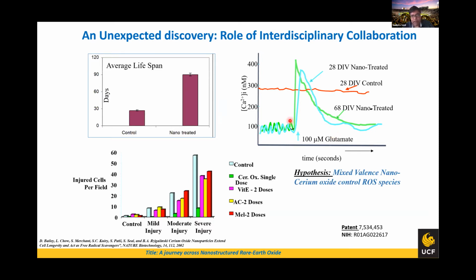At the same time, we got a grant. One of the comments from the panel was, how does it compare with the normal antioxidant type material if you're selling the cerium oxide as an antioxidant? And we saw that a single dose of this material really does a lot of good things to the cell as well. So back then we developed a hypothesis that at the nanoscale of cerium oxide, you have mixed valencies, which really control the reactive oxygen and reactive nitrogen species.